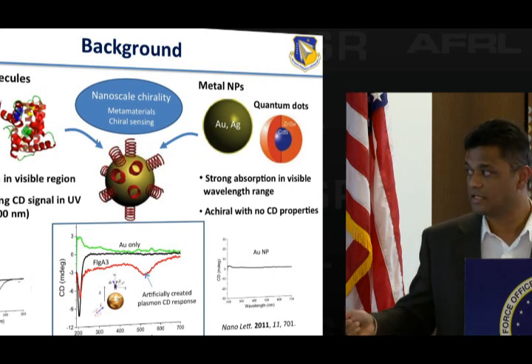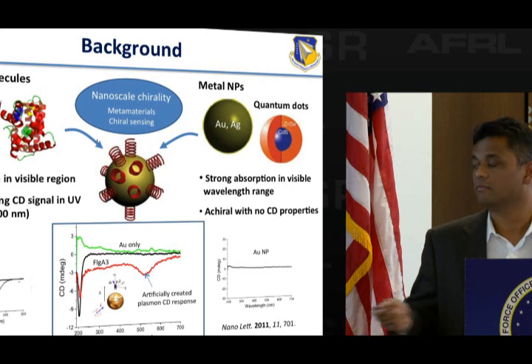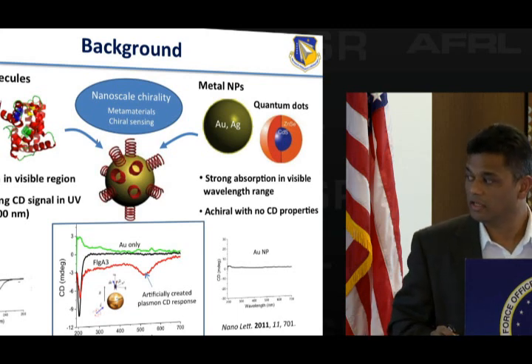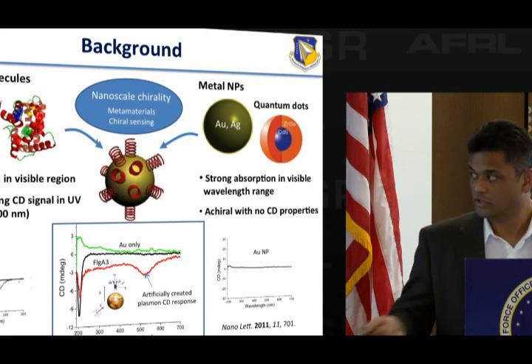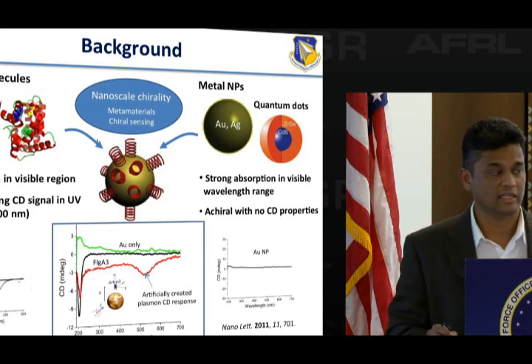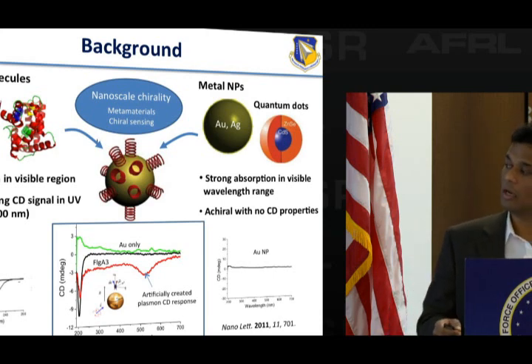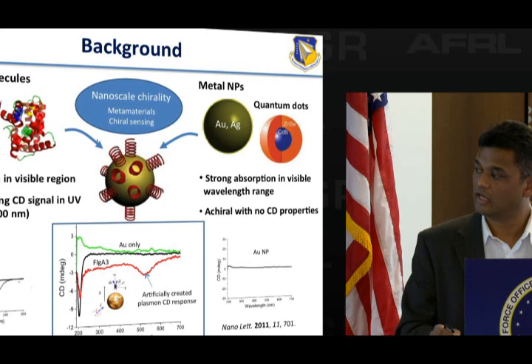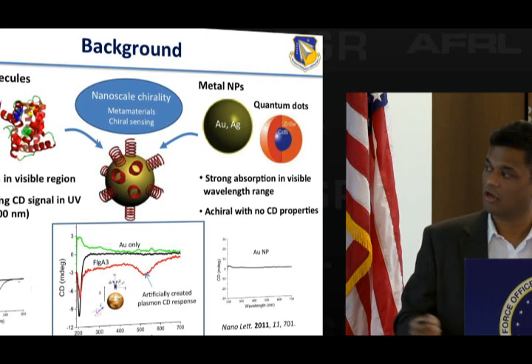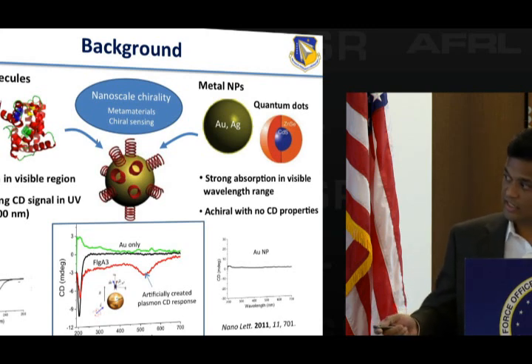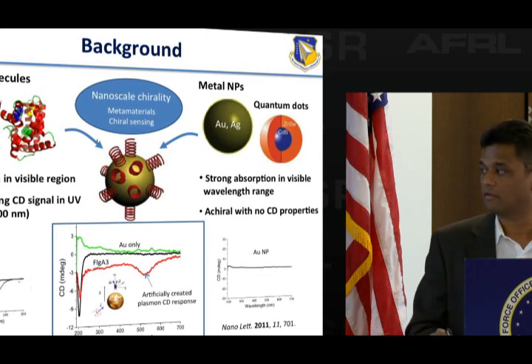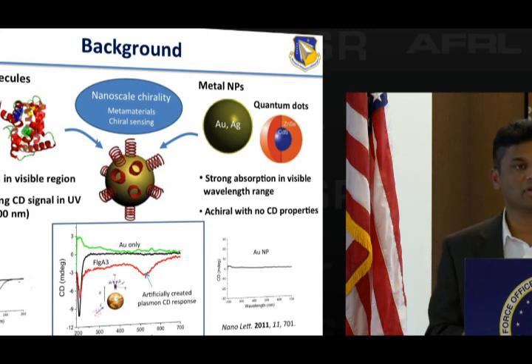It doesn't happen by itself, because gold nanoparticles by themselves give a flat line, and the peptide does not have any peak in the visible regime. It's only when you combine the two that you begin to see that signal. And through some calculations that we have done in collaboration with Alex Govorov at Ohio University, it is the interaction between the dipole, which is your peptide, and the gold nanoparticles. You have this Coulombic interaction that gives rise to this plasmonic peak.